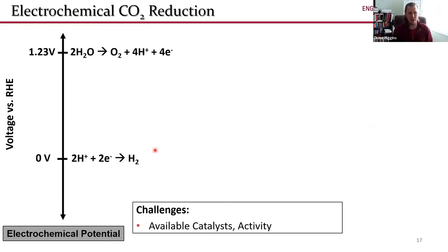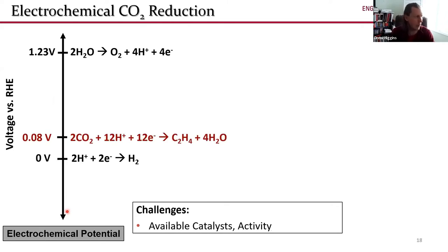Then if we do want to talk about the catalysts we have available, activity is a bit of a challenge. And so I show here a scale of electrochemical potential. Essentially, going further down this scale means having to put more energy into that system to drive the electrochemical reaction. So if we think about the conversion of carbon dioxide into ethylene, for example, at any electrochemical potential below 0.08 volts versus the reversible hydrogen electrode, thermodynamically, we are able to convert CO2 into ethylene.